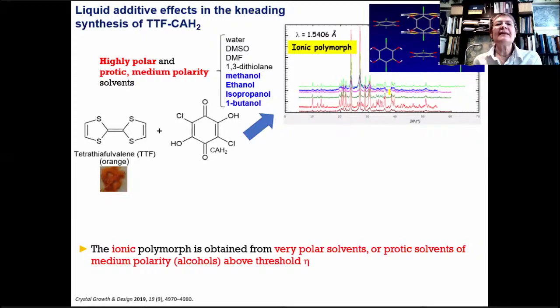Okay, so then the second system that I studied for charge transfer complexes of tetrathiafulvalene is the reaction of the orange TTF with chloranilic acid, which is this molecule shown here. So instead of having chlorine, now we have two hydroxyl groups in the para-benzoquinone substituent. And using solvents of high polarity, such as water, dimethyl sulfoxide, and dimethyl formamide, we obtain this ionic polymorph of the charge transfer complex. And the structure of this material has been known for a while. It was solved using single crystal X-ray diffraction.